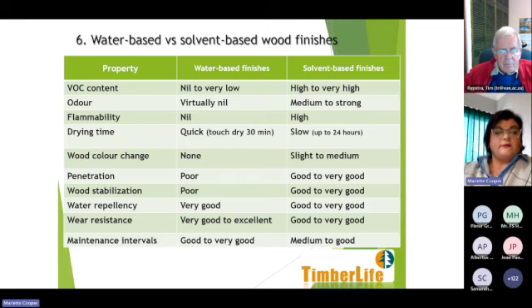With reference to drying time, water-based finishes is relatively quick drying, being touch dry on the wood surface within about 30 minutes. And with your solvent-based finishes, it can take up to 24 hours, for example, with high-build varnishes to dry and cure properly to the wood surface. If you talk about the application of the clear product, the wood color change with water-based finishes will be none. It's completely transparent and clear on the wood surface, whereas solvent-based finishes, depending on the components, which normally have an oil component to it, will tend to have a slightly yellowing or medium color effect change on the timber itself.